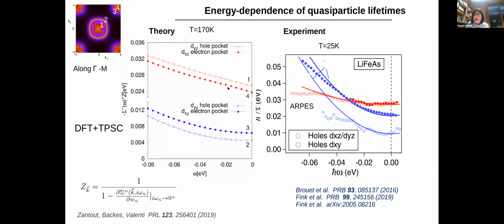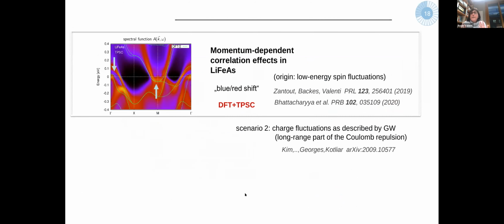So this is the result of the experiment. And these are the results that we obtained with TPSC. So we also obtained this type of linear dependence in omega. While the pockets, the hole pockets at 2, so basically the outer hole pocket and these outer electron pockets, they have more quadratic behavior, as it is also seen by experiments. So these theories seem to capture these features observed in ARPES. So with this type of calculation, what we can say is that a momentum dependent type of effect in the self-energy is able to explain many features of these ARPES observations.